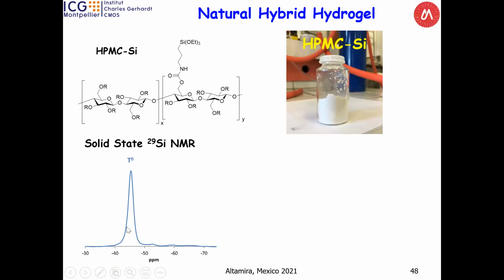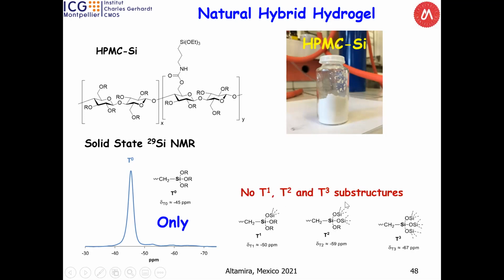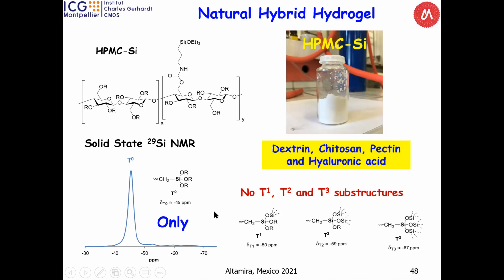By silicon NMR, we showed that we have our silane group intact. It's only T0. Maybe it's very strange for you. T0 means there is no connection with another one. If you have T1, T2 and T3, that's when your cross-linking starts. The idea is to demonstrate that in our synthesis we have a silylated precursor without any destruction of this part. And we generalized this synthesis to another type of biopolymer: dextrin, chitosan, pectin, hyaluronic acid, and so on.